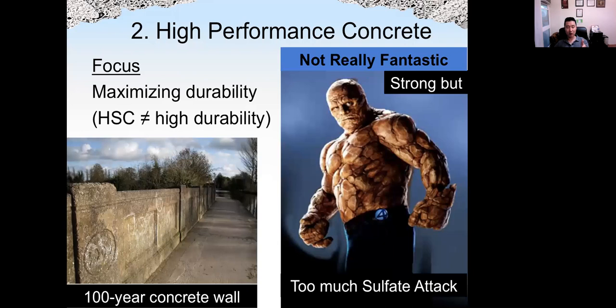But as we mentioned before, high strength is not equal to high durability. Some very old concrete may not be as strong as today's high-strength concrete, but they can last hundreds or even 1,000 years. If a high-strength concrete has some durability issues, it cannot last long. For example, if concrete has high drying shrinkage or high autogenous shrinkage, even though the cement paste is very strong, shrinkage will cause a lot of cracks. So that will make the high-strength concrete not very durable.